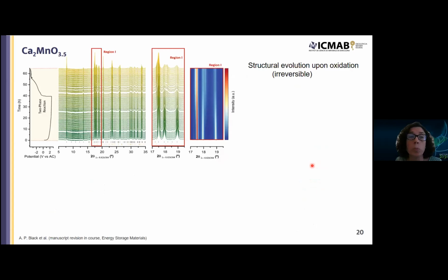So again, this is operando diffraction, in this case for the manganese compound. And what we see is similar to what we saw with the cobalt compound. So we see some evolution of the diffraction pattern upon oxidation. Here you see this process. And then after oxidation, when we reverse the sense of the current, despite we get some electrochemical response, there are no changes in the diffraction pattern. So this evolution seems to be irreversible.